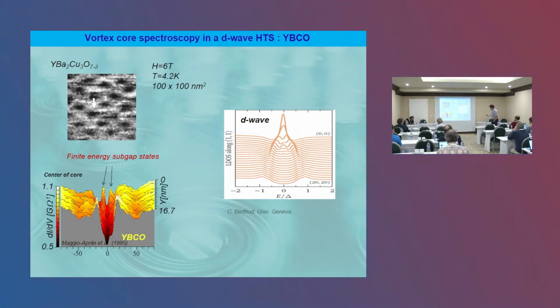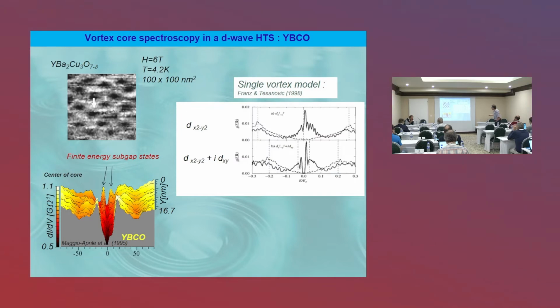And so for a very long time, people and theories were trying to explain why a D-wave superconductor would reveal such a finite energy state instead of this zero bias anomaly. Like in this Franz and Tesanovic model, where a small i dxy component had to be added, probably a field-induced component, in order to get a fully gapped symmetry state and the occurrence of finite energy states at the center of the vortex core. But this was theory, and we never had a very clear conclusion on this.